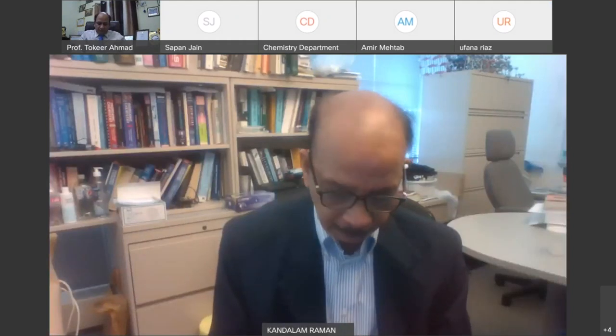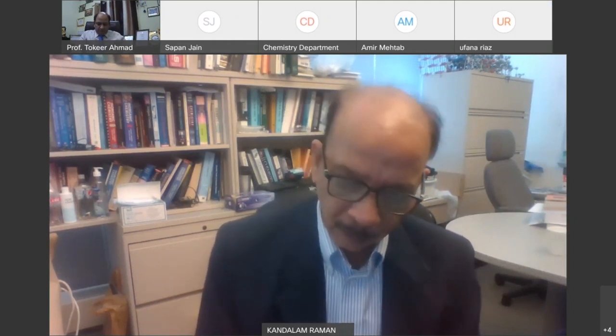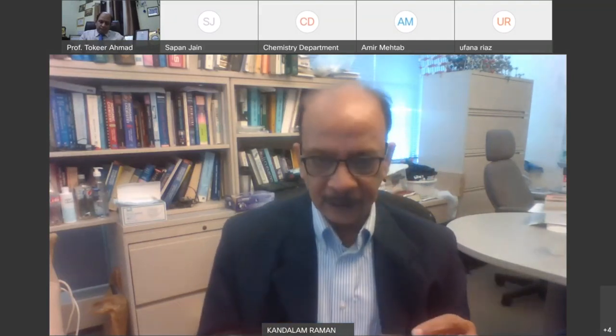Once you have the single phase, in my lab, I insist that we do chemical analysis to make sure that all the elements are in the right ratio. So that is one important aspect. We also do SEM studies, scanning electron microscopy, basically, to find out the morphology of the compounds. And there again, if there is polymorphism or different phases present, you can figure that out. You can also zoom into different domains to see if there is any compositional inhomogeneity across the samples. So the question is very simple, loaded, but the answer, of course, we have a lot of tools today than what we had.